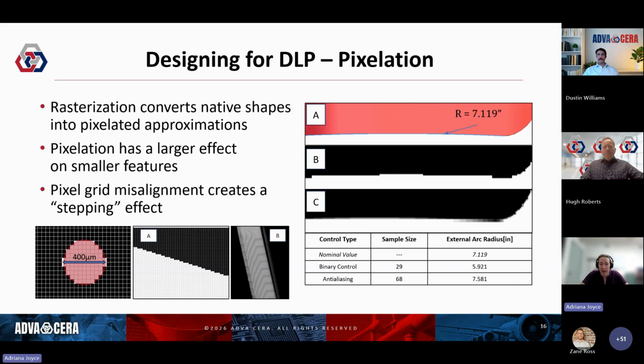A straight edge that is not aligned with the pixel grid becomes very stepped, and you get a stair step effect that looks like the printed part shown in figure B along the bottom. Radii that are approximated by very few pixel steps, like this one shown in B on the right side of the image, don't approximate the size of the feature very well because we're using pixels that are larger than the change we need to make to our feature.